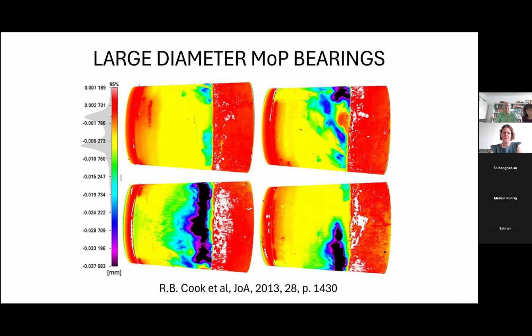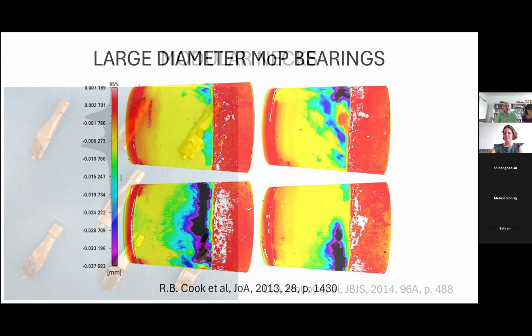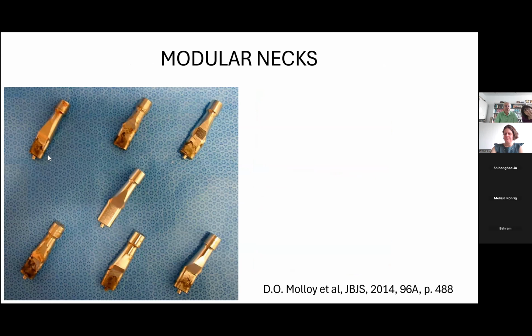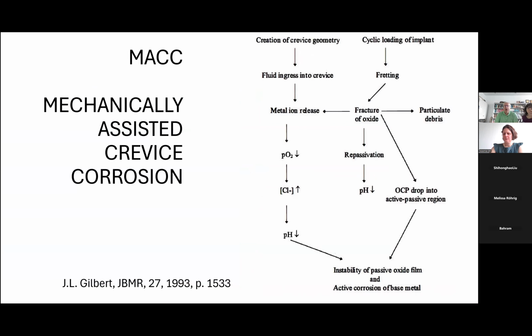It means you have some corrosion at this interface. Also, you sometimes have another type of modularity, between the stem and the neck. And also here you see some corrosion on retrievals. And here is what was developed in the early 90s for mechanically assisted crevice corrosion.